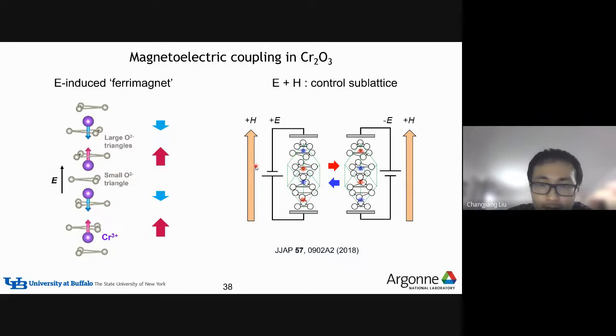People found that by simultaneously applying both an electric field and a magnetic field, people can actually switch the orientation of the sublattices. So this provides an opportunity to manipulate the sublattice of chromium oxide by using an electric field. And further, because chromium oxide can produce a magnon spin current, this means we could use an electric field to manipulate the magnon spin current directly, right? This could be very advantageous for spintronics application.